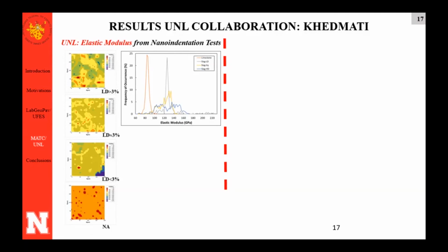So we had, with no curing, the higher level of expansion, elastic modulus here is the gray line, has a broader range, but the average seems to be around 130 gigapascal. And as I cure the slag, this broader range starts to narrow down, so less standard deviation among the results. But even with this variation, the average seems to be quite similar between the three slags.